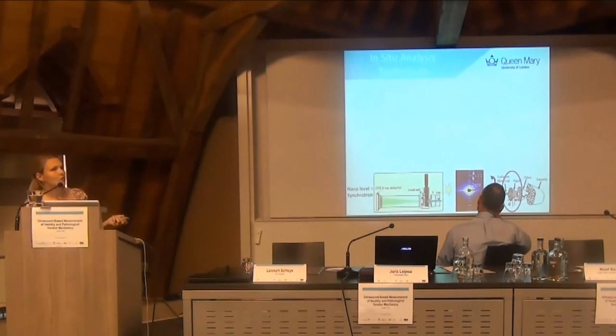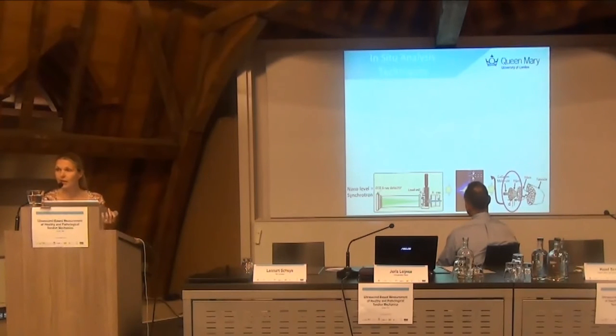And there's lots of things you can do. So here's sort of what you do at nanoscale. You use, say, a synchrotron rig. And here's my rig where I can load a tissue explant within the synchrotron. If you hit your sample with an X-ray beam, you get these beautiful little patterns like this. What these little distances between the little bars here mean is something about how fibrils are elongating and reordering within the tissue, and how spread this is tells you how well ordered the fibrils are. So you can put your piece of tissue in, you can stretch it, and you can start to see how the fibrils within the tissue are responding to that strain. It gives you an insight into the nanoscale response within that piece of tissue under load.